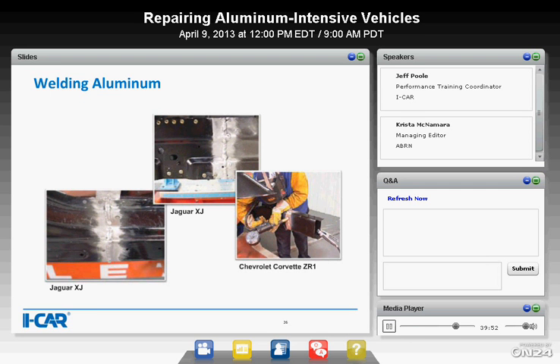When the weld's initiated, what we find is that progression is not as uniform as when we're welding steel. Aluminum has a higher propensity for cold starts, and there are techniques to minimize this. Additionally, the travel speed is usually faster than we're accustomed to with steel. As the heat builds in the material, we find that the travel speed is going to change, penetration changes, and the potential to burn through increases. So judging the weld puddle tends to be a little more challenging because it is a more fluid weld puddle than typically with steel.